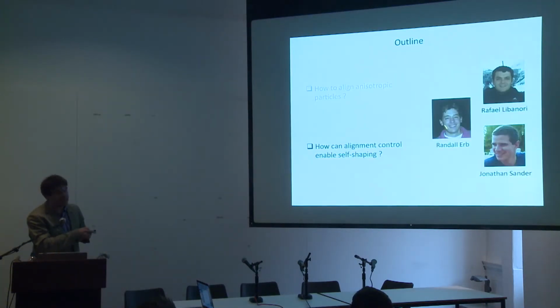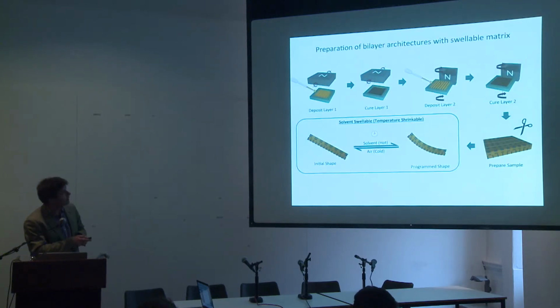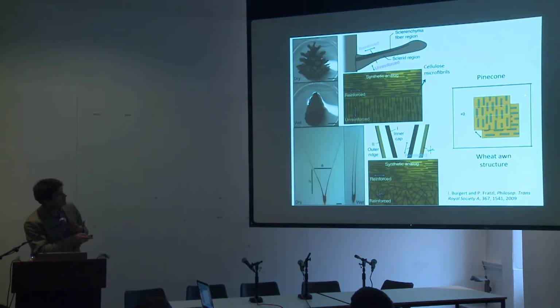So now the question is, can we exploit it to make self-shaping composites? I've told you already that the design concept behind this self-shaping effect is to align platelets or fibers in a given direction. And since we know how to do that, all we have to do here is basically to use this approach in bilayers. So here would be a first layer of your material, here would be a second layer, and in each one of the layers you have an orthogonal orientation of these platelets. And now if we just cut it and have a polymer matrix which is responsive to an external stimulus, we should be able to see these effects. And indeed, that's what we see if we take a bilayer and cut it at what we call a zero cutting angle, because it forms a 0-degree angle with the bottom layer.